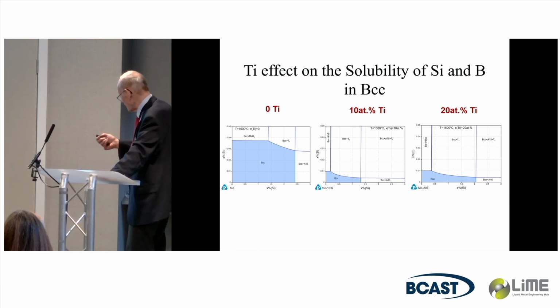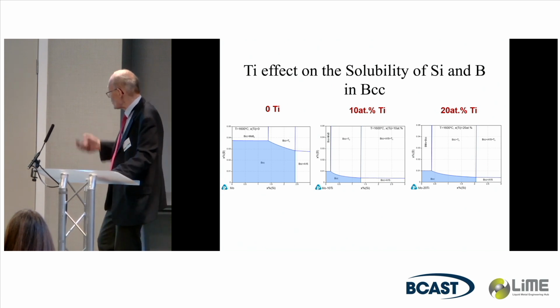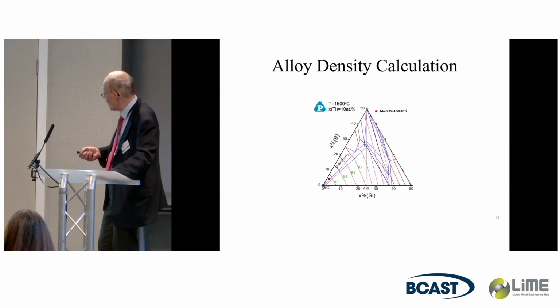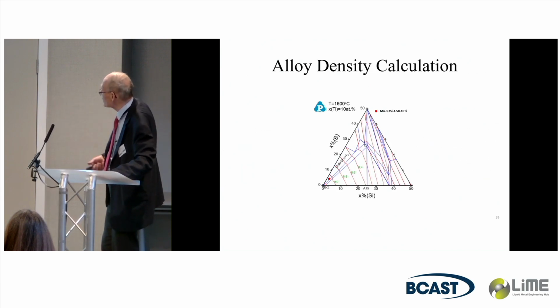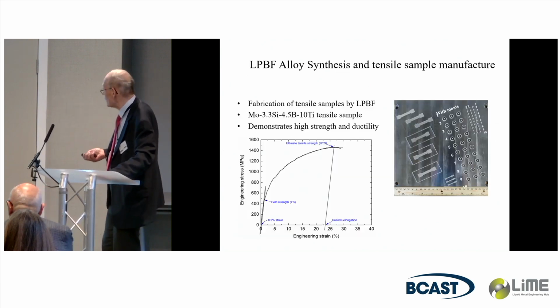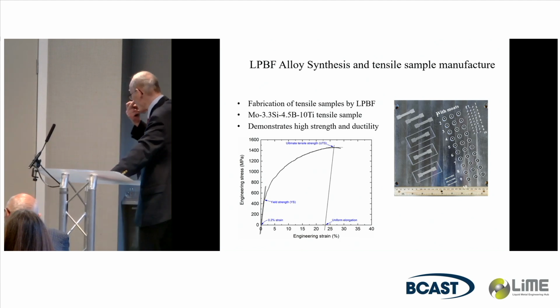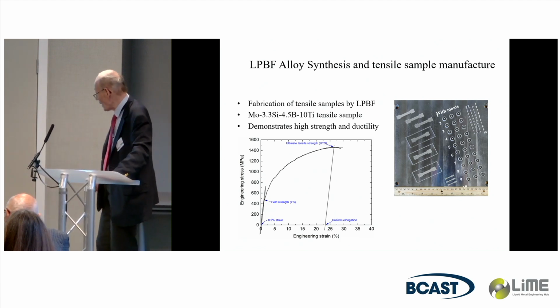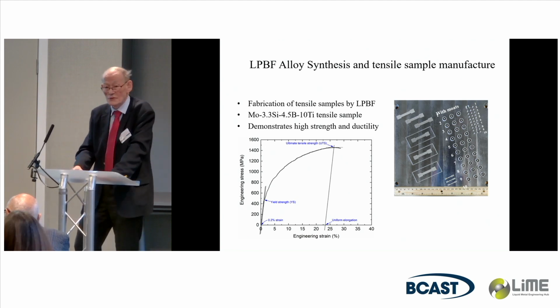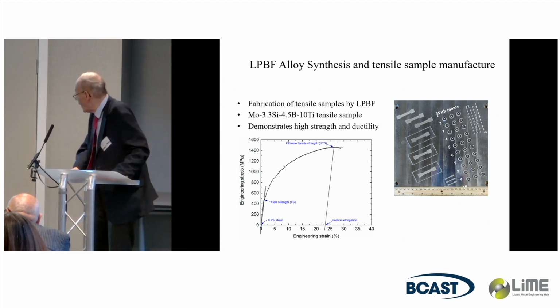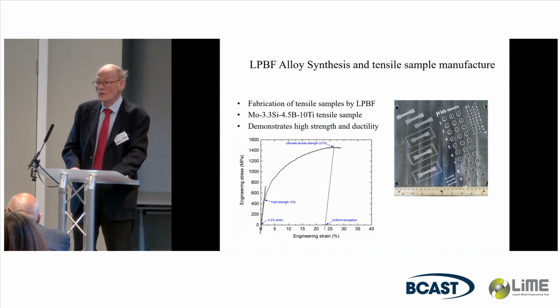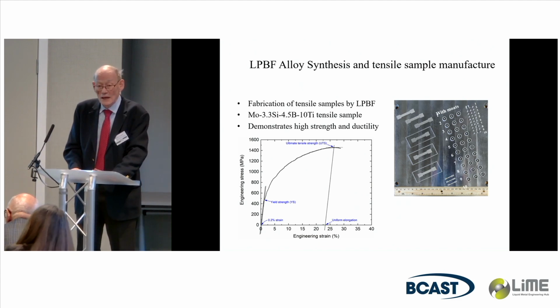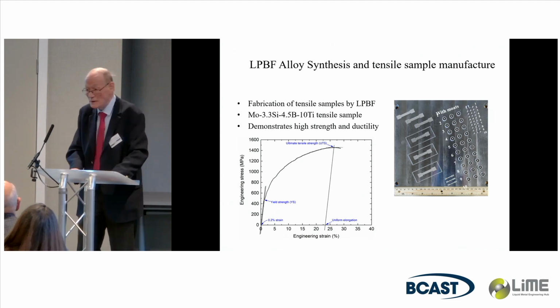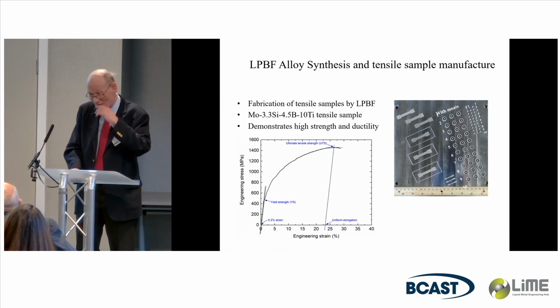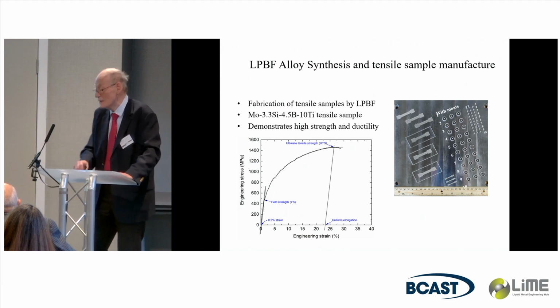More titanium doesn't help us because it pushes this out again. So 10% titanium satisfies the density profile, which they've calculated, and we can now produce samples with this composition that have about 1.5 gigapascals of strength and ductilities of more than 20%. We're now preparing samples for creep and fracture toughness and thermomechanical fatigue.